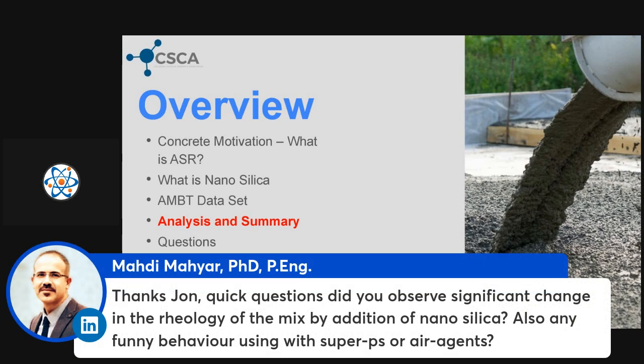Quick question. Do you observe significant change in the rheology? Yeah, Mahdi, absolutely. We did an entire YouTube video on using nano silica to bring back a mix from segregation, using different nano silica sizes at different dosages and how it changes the rheology of the mix. And of course, there's some great work done by Konstantin Sobolev on the impact of nano silica on high range water reducer efficiency. If you look at our article that we published back in 2015 on colloidal silica admixture, it shows how we increased slump evolution while reducing our superplasticizer dosage by over 50%. Wow. And then air entrainment, the great thing about all nanoparticles, not just nano silica, is that they stabilize everything around them, including air as well as water for internal curing.